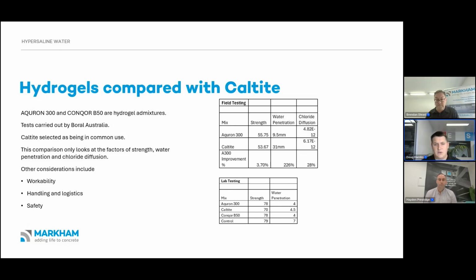Then we progressed to the laboratory testing, where we looked at strength again and the water penetration. As you can see there, in that controlled environment where you haven't got that variability of the field, we are on par with the Caltite admixture there, so performing very similarly. And what's interesting is even on a nearly 80 MPa concrete, you're still getting that 7 mm of water penetration into that concrete. That's using the British standard 12390-8, which puts samples under a 50 metre head pressure. So yeah, it still demonstrates that it's got that porosity, and then you can see the subsequent reduction in permeability there.